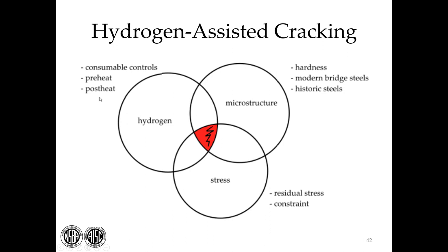So all of these are practices you can use to avoid cracking, primarily the hydrogen control and the microstructure. And potentially, if you need to, you could even redesign joints to avoid some constraint. But under D1.5, if you use the steels that are prescribed there and the practices that are prescribed, you won't have hydrogen-assisted cracking. We go into detail about this mechanism in the manual in case you encounter it, to help understand what you can do to avoid or solve a problem.